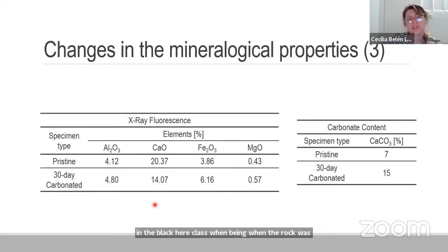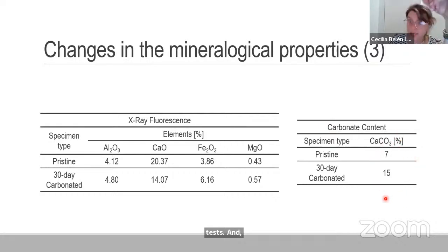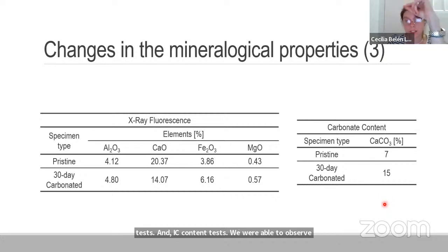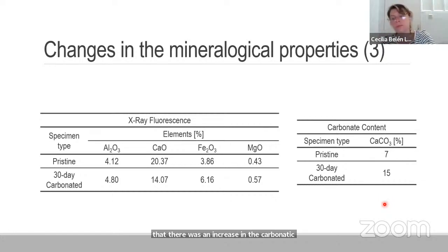We also performed a series of X-ray fluorescence tests and carbonatic content tests. We were able to observe that there was an increase in the carbonatic content of the sandstone.